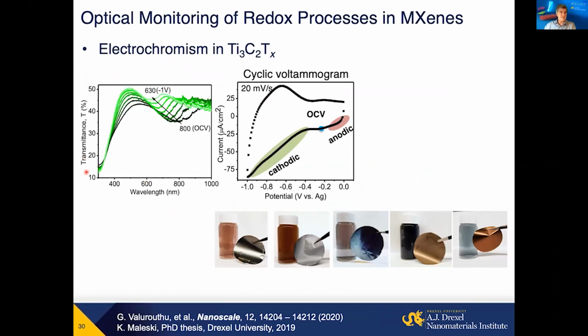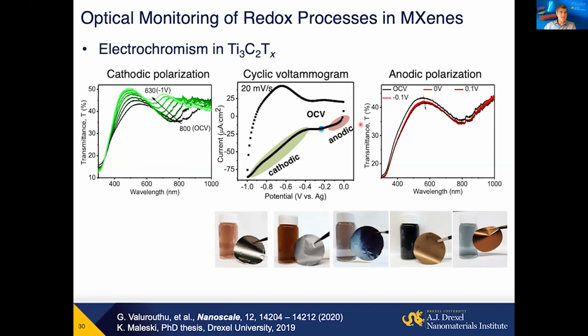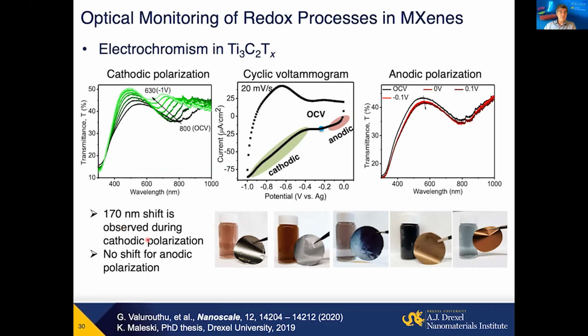This is a UV spectrum of titanium carbide Ti3C2 MXene. And you can see by applying about -1 volt voltage, we can shift the plasmon resonance peak by 170 nanometers. So basically what we do, when we shift it here, we change the color of this MXene. It goes from green in normal state to blue in reduced state. So we can make an electrochromic device.